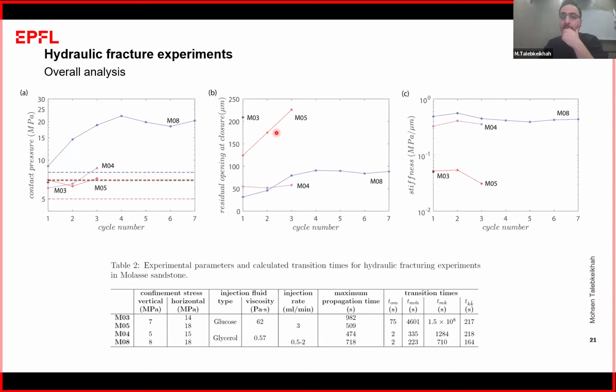And in this figure, you can see the stiffness value for each cycle. For all 7 cycles of M08, they have the same value, and it is close. It's interesting that these 2 experiments are different experiments but with the same fluid, and the stiffness values for each cycle are close to each other. And also M03 and M05, where we were injecting the same fluid, have somewhat the same stiffness value at the peaked time and pressure.